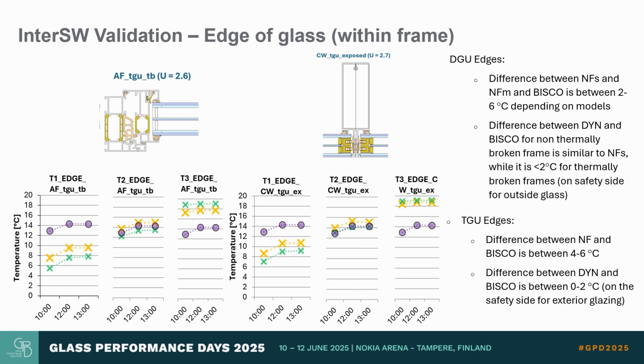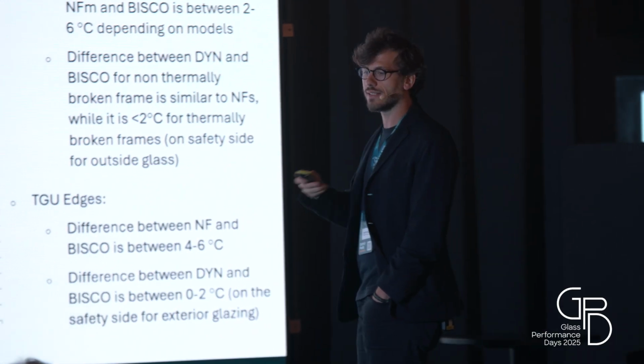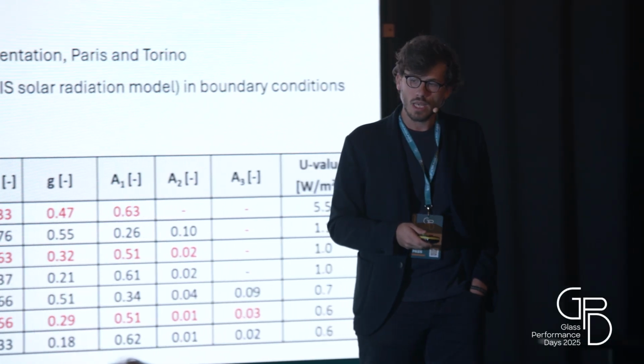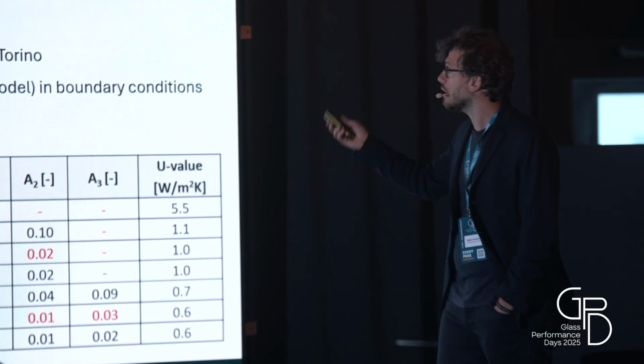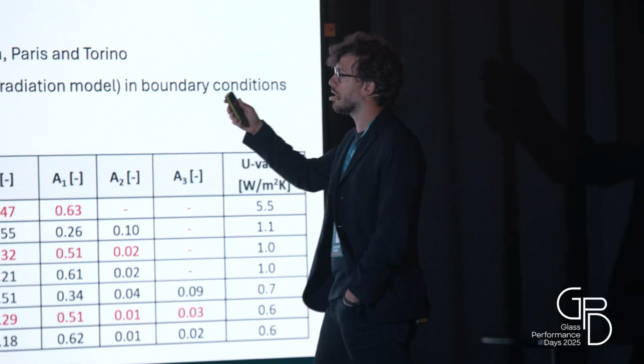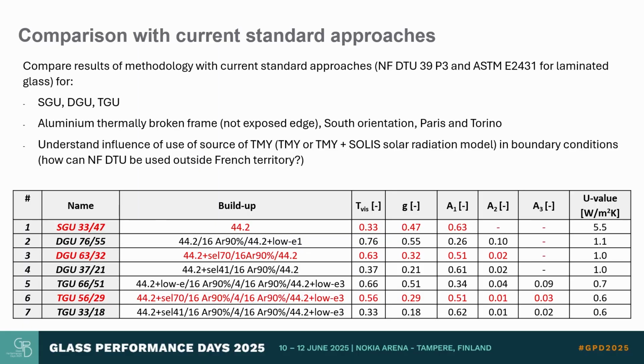So you can see that with the national standard, you have this 4 to 6 degree difference, and sometimes this is overestimating, sometimes underestimating, so it's not always in the same direction. While with our model, we are basically at 1/3 of this difference, and again, this can be over or underestimating. So we tested this methodology for different configurations of glazing, from single to double and triple glazing units with different optical properties. And you can see the different absorption of the different layers.